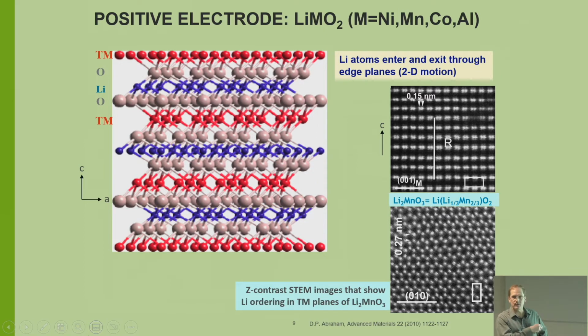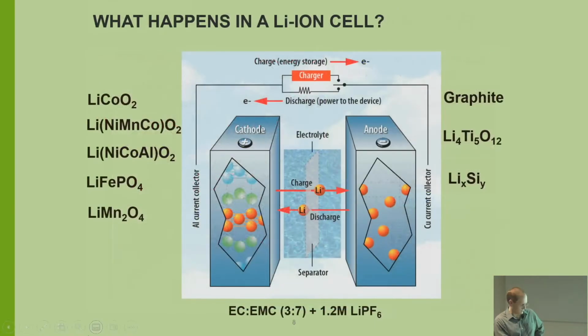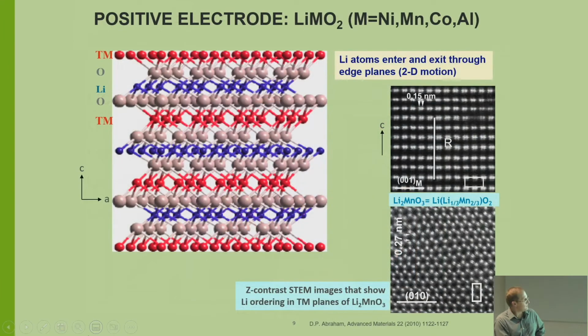Lithium-ion cells can go thousands of cycles if you take care of them and keep the temperature under control. Now, what's really cool is, thanks to modern science, the STEM, scanning transmission electron microscope, you're actually seeing those manganese atoms there, and the dark spots are the lithium atoms. Now, if you look from the top, you're seeing hexagonal patterns of how those manganese and lithiums align.